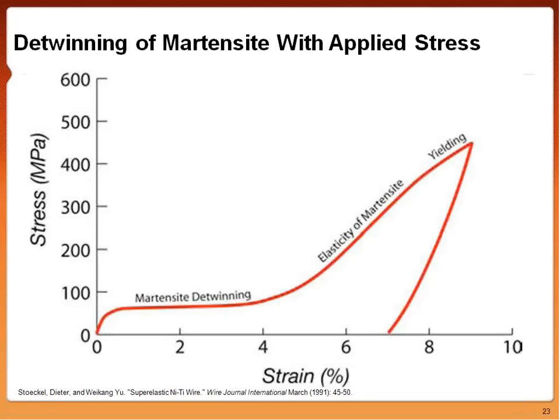So remember I said before with those twin boundaries forming? When we apply a stress to those, the boundaries parallel to that twin plane are very mobile. As soon as the stress is applied in that 2D projection, it's allowed to shear past one another to accommodate that stress very easily.